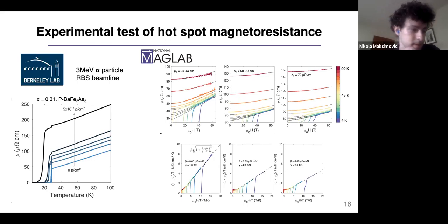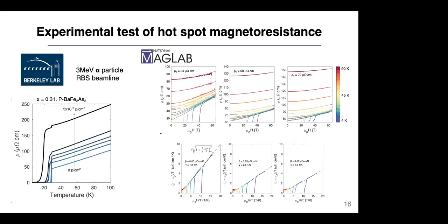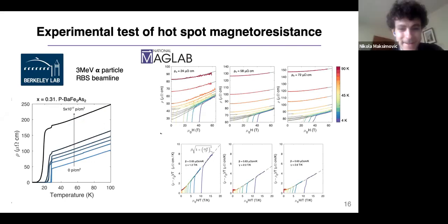You need to, I think it's important to consider what the Fermi surface and scattering rate look like. Also, if you have very clean samples, the cold spots of the Fermi surface can give a significant contribution. In the cuprates, we did a lot of work dirtying the samples, and when you dirty them, they are still H square. Okay, that's interesting. Yeah, it might be interesting to compare.